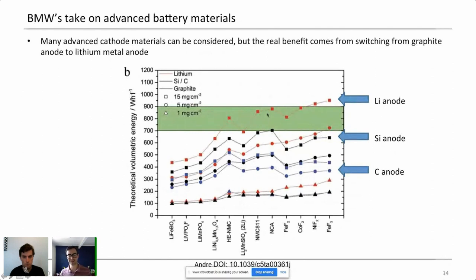And as you can see, the only change in a battery that really gets you into this ballpark is going to a lithium anode, which bumps you onto this red curve here. If you use a lithium metal anode, you can get substantial improvements by entirely eliminating the host material. So you get rid of the carbon, the graphite, you don't replace it with silicon, you store only lithium on the anode of the battery, and you're able to get a substantial improvement in energy density.